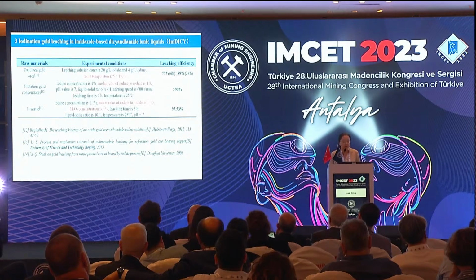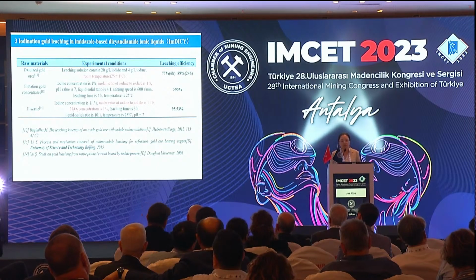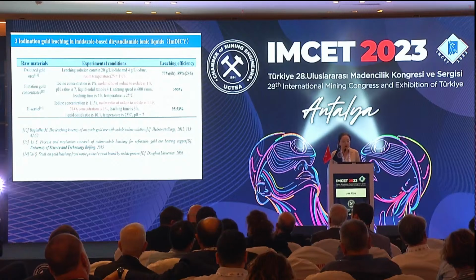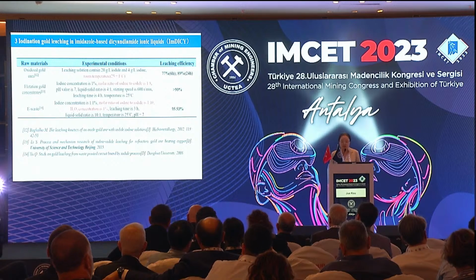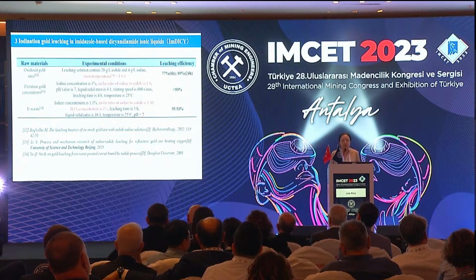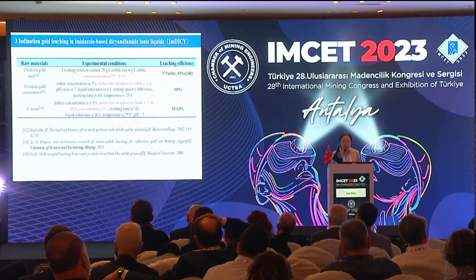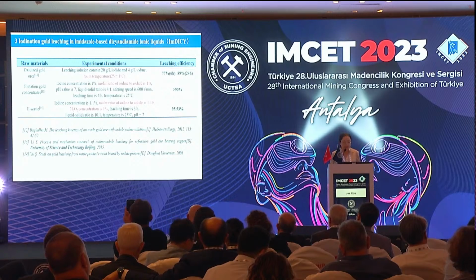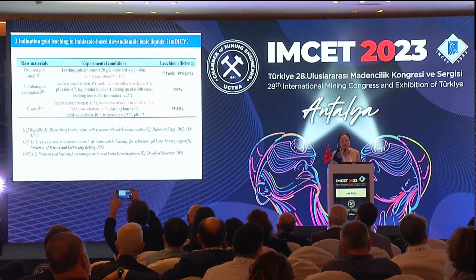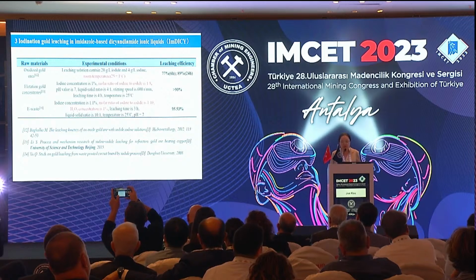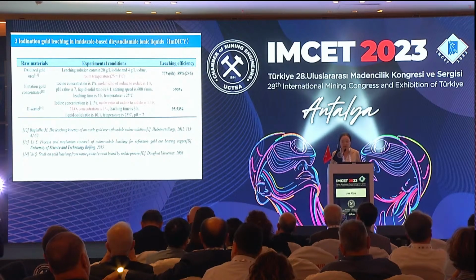According to the literature, iodine leaching has very good performance on different kinds of raw materials. For example, for oxidized gold ores, at room temperature, the leaching rate can reach 89% within 24 hours. For flotation gold concentrates, which are mainly sulfide, the leaching rate can reach higher than 90% within 4 hours at room temperature, which is quite similar to cyanide leaching. And for e-waste, since the impurity is quite low, the leaching rate can reach 95% within 3 hours.